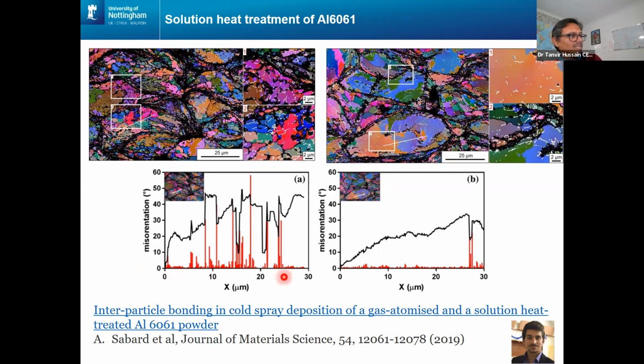And we plotted distance versus misorientation in both cases. What we see, the heat treated powder shows low angle grain boundaries mostly located at the particle-particle boundaries, whereas the as received powder shows an interior containing a limited amount of low angle grain boundaries, where the particle-particle interface presents a wide distribution of low angle grain boundaries, which also suggests accumulation of lattice defects.